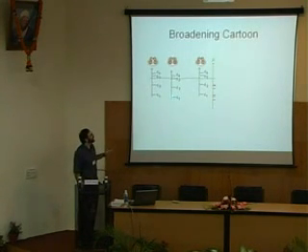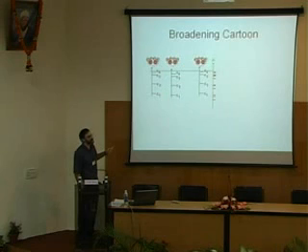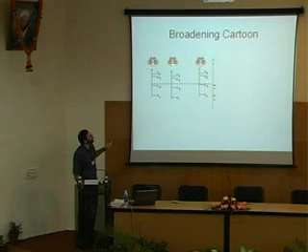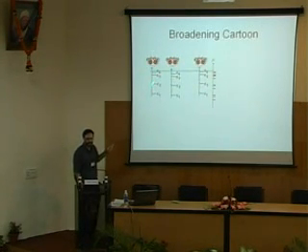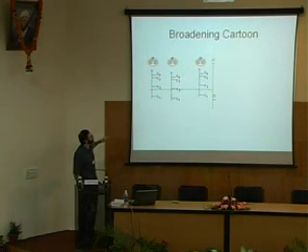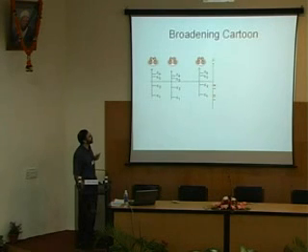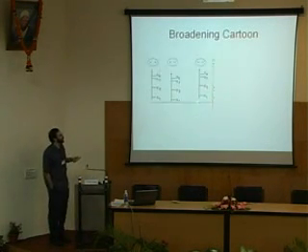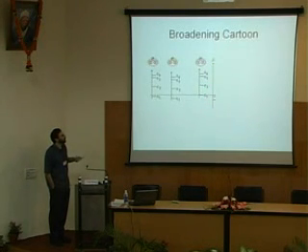The second thing is that these boxes shift up and down as charge ends up getting added to the system. As an electron goes here, now it's partially neutralized this dopant, and that affects this as well. Now an electron's less likely to go over here because one electron already went over here. And you can see it schematically as these boxes shift around. So can we still see anything in the light of all this randomness and all of these chances to smear out our sharp levels?